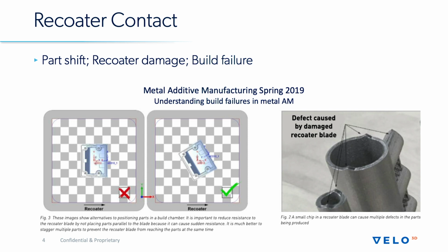To that end, many things have been developed, or many tricks have been used in the industry to date to try to minimize these types of failures. Things like using heavy usage of supports to anchor the parts firmly to the build plate to try to prevent them from ever sticking up out of the powder bed. And even things like in the bottom left-hand corner where parts have to be oriented in very specific directions relative to the recoater to prevent the recoater from plowing into them and causing a failed build.